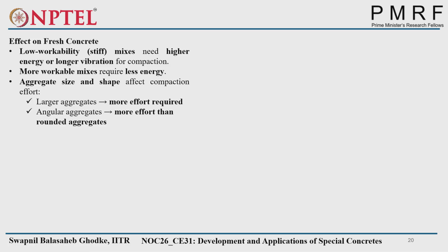Further effect on fresh concrete is that low workability, that is stiff mixes, very hard mixes, requires higher energy or a higher amount of time for vibration to get that concrete fully compacted. Particularly if you see the no slump concrete, we saw the roller compacted concrete, right? In that case, the roller has to be placed over that concrete multiple times to get it properly compacted, and there we are using one of the geotechnical rules, that is compaction with the optimum moisture content.